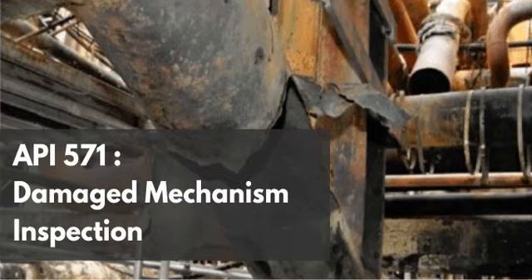The crack propagation doesn't just shear transgranularly through the crystalline structure of the ferrite or pearlite grains. It goes around them. Right. It snakes its way along the grain boundaries, essentially dissolving the atomic glue that holds the crystals together. That sounds terrifying. It is. Under a microscope, this creates a highly branched, intricate network of small cracks. It looks exactly like shattered safety glass or a spider web on the surface of the metal.